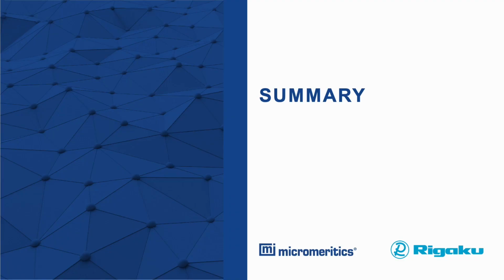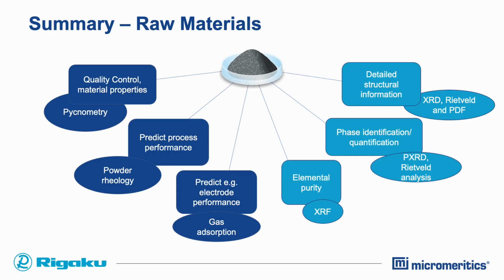And with this last topic, I would like to conclude this webinar. What have we seen? The first part about the raw materials. We saw how pycnometry was used for the quality control and also to describe material properties. We also saw how we could predict process performance by powder rheology, but also how we could predict electrode performance by the gas adsorption. We also saw how the elemental purity of our precursor material could be estimated or analyzed by XRF. Further, we saw the phase identification and quantification, powder XRD and Rietveld analysis, but also we saw detailed structural information by XRD with the help of Rietveld and PDF.